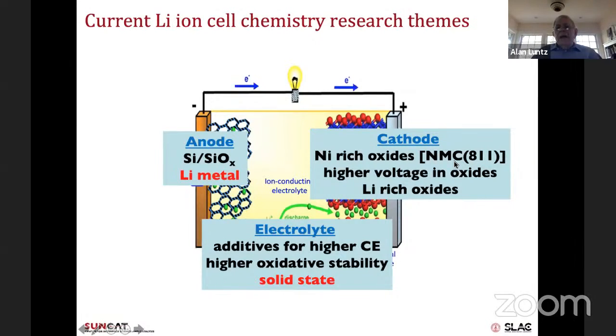And this continues. They want to even go lower than that. You can actually go lower than that. They're trying to actually make things that, for example, use other redox besides just the transition metals to get the lithium in, things like using the oxygen. And also they want to push these things to higher voltage. The problem with all of these attempts to do this